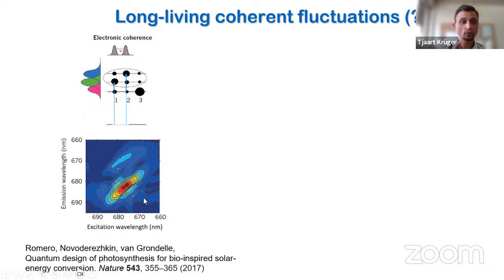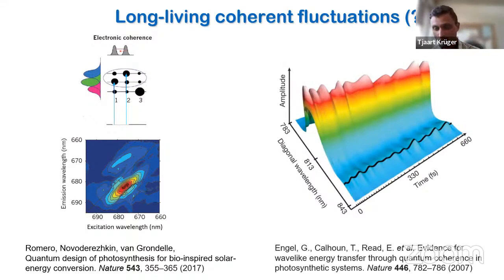So if you would excite 2 or more excitons simultaneously, if you have a phase relationship between them, an electronic coherence will form. And then in the frequency domain, you will see a beating frequency. So the amplitude will oscillate at a frequency equal to the frequency difference between these 2 excitons that are simultaneously or that are in phase. Okay, so in 2007, there was a report in Nature of evidence for wave-like energy transfer through quantum coherence in photosynthetic systems. So this is what was observed: a beating behavior in the frequency domain as a function of time, and the coherence time of this beating behavior was about 660 femtoseconds. Okay, this experiment was done at 77 Kelvin.